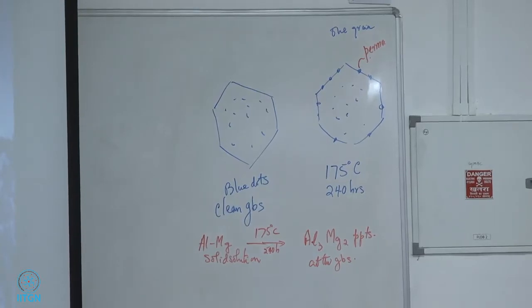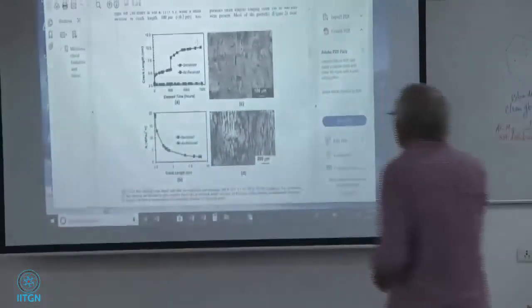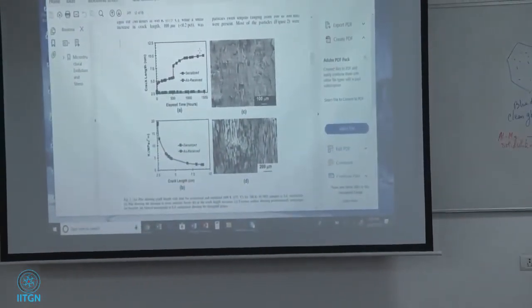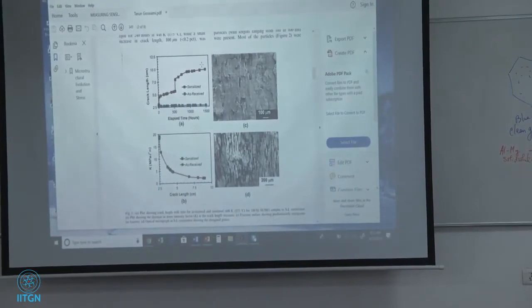If somebody is doing a thesis on this, you can't wait 5 years for the precipitates to form, right? Because if this material is only exposed to 90 degrees or 80 degrees Celsius, the kinetics, the rate at which the precipitates will become bigger, will slow down, right? Because the temperature has gone down, right? But there is a study here. There are other studies too. I'm just picking out the paper that first came on my computer.